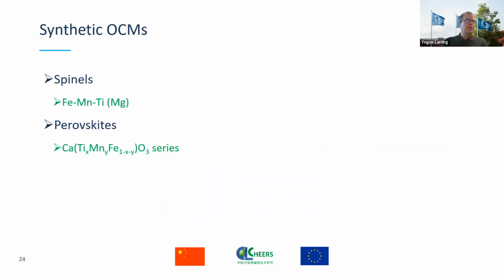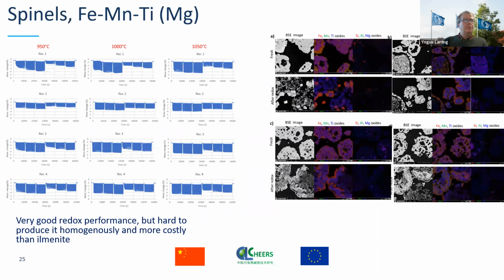When it comes to synthetic oxygen carrying materials, we have the spinels and the perovskites. The spinels show very good and even capacities and very good stability in a way. But it was a little bit hard to get them very homogeneous in the process we used, because we mixed ilmenite and manganese. If you take that into consideration along with the cost of production, ilmenite is a cheaper source, and this will have a problem competing with it, since the lifetime is not extended much compared to the raw materials.